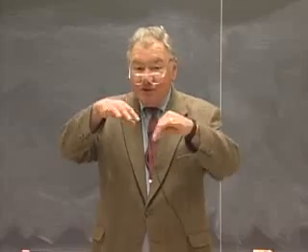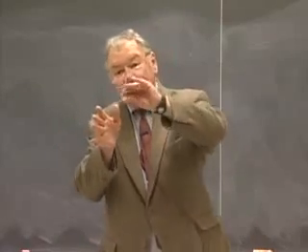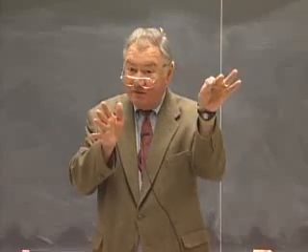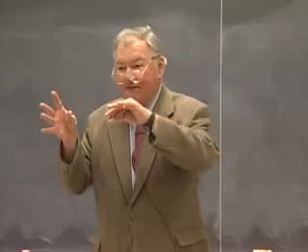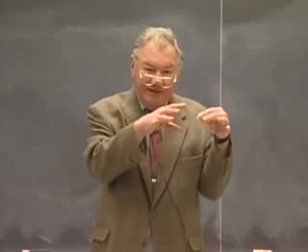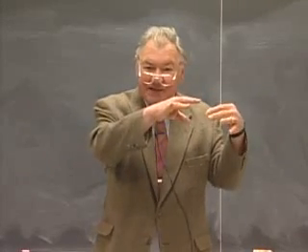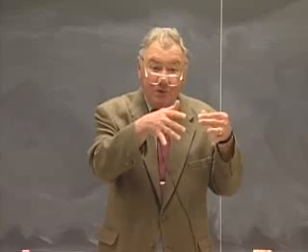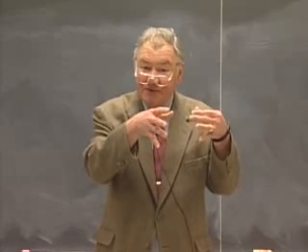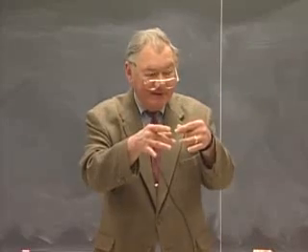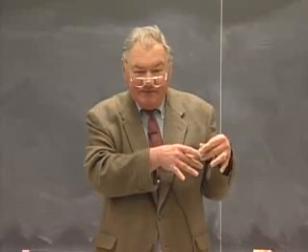And then if you want to transform the axes, which is to say you want to cut out your specimen, be it a plate or a rod, in a different orientation, you have to transform the full four-subscript tensor elements to a new setting. And then if you want to continue to work in that setting in the compact matrix form, collapse it back down to matrix form, insert the equalities, and then you're back to where you started from.